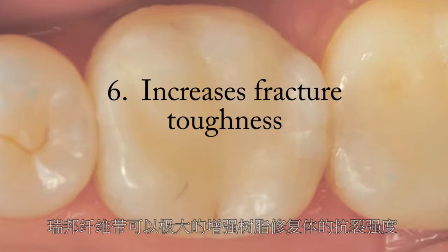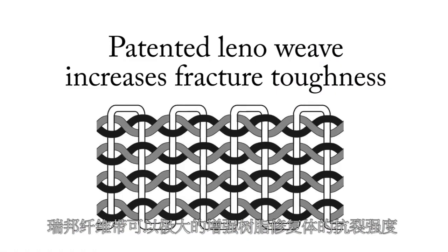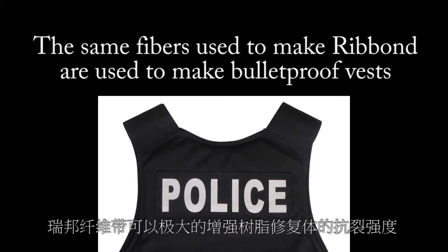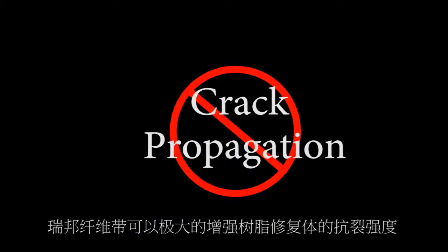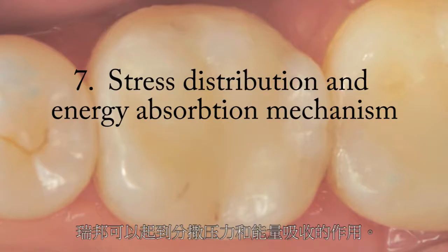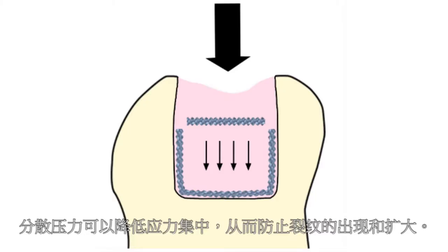Increases fracture toughness. Ribbond fiber reinforcement greatly increases the fracture toughness of dental composite restorations. Ribbond's unique combination of fixed nodal intersections and tough, ultra-high molecular weight polyethylene fibers inhibits and prevents crack propagation in composite resin. Stress distribution and energy absorption mechanism. Ribbond acts as a stress distribution and energy absorption mechanism. It minimizes the stress concentrations by distributing forces over a greater area, which prevents crack formation and propagation.